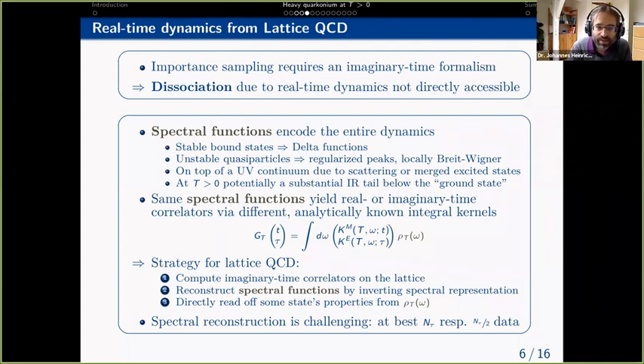In this case, the idea is that we can compute Euclidean correlation functions G_T of tau at finite temperature, and this is related by an integral kernel to the spectral function rho at finite temperature of omega. And if we have this spectral function, we could then do with a Minkowski space integral kernel transform back to the correlation function in real time, or alternately, directly infer the property that we want to know from the spectral function that is obtained from the lattice calculation.